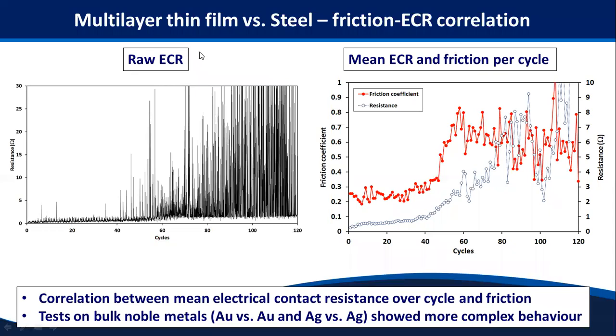So how do we understand that? Well, we can look at the raw electrical contact resistance signal as a function of time, in this case converted to cycles. We can see these occasional spikes, but then it's a rather complicated picture. You could look at spike density or something like that. But one thing that we thought might be interesting was to compare the mean electrical contact resistance per cycle and the friction per cycle. And when we do that, we can see there's quite a clear correlation, at least in these tests. It's a little bit more complicated in the tests on bulk noble metals.